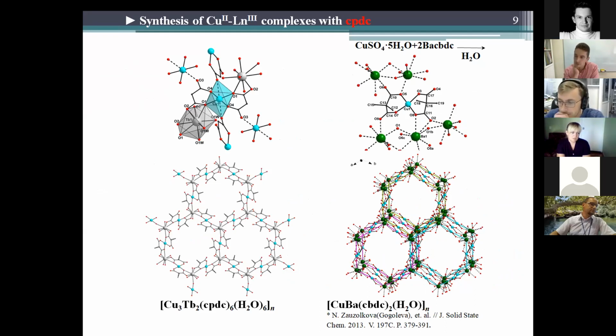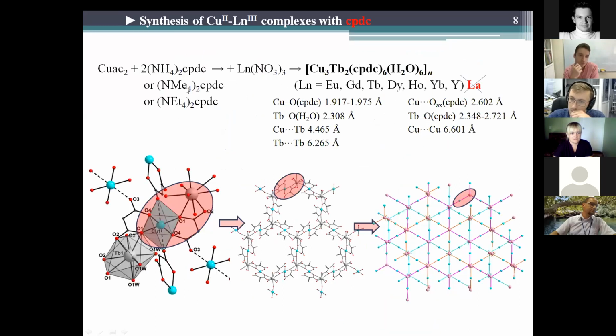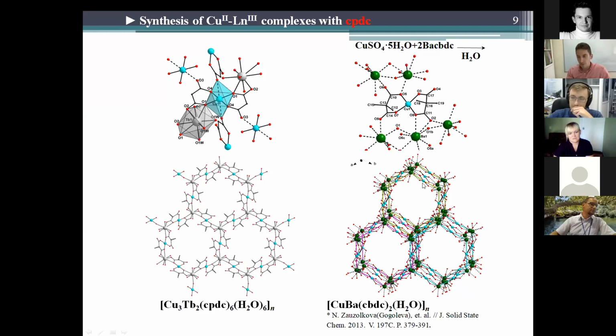Thank you for your question. Yes, such studies were performed in the case of dimethyl malonates, but the porosity of these complexes is rather low, about 9%, not very high porosity. And concerning copper-lanthanide complexes, these cycles overlap each other, and there is no porosity at all. So maybe yes, they can sorb small molecules, but not very effectively.